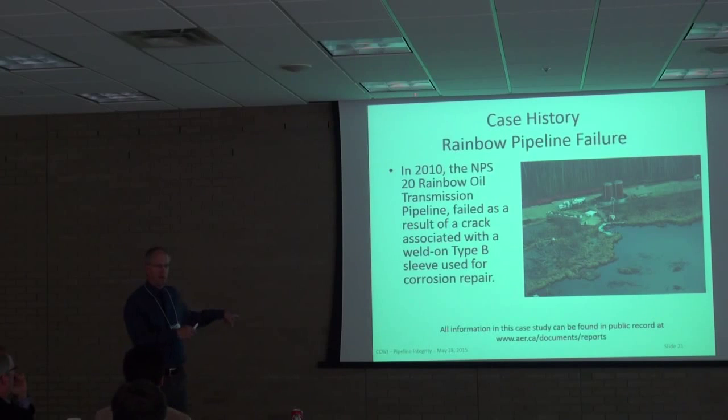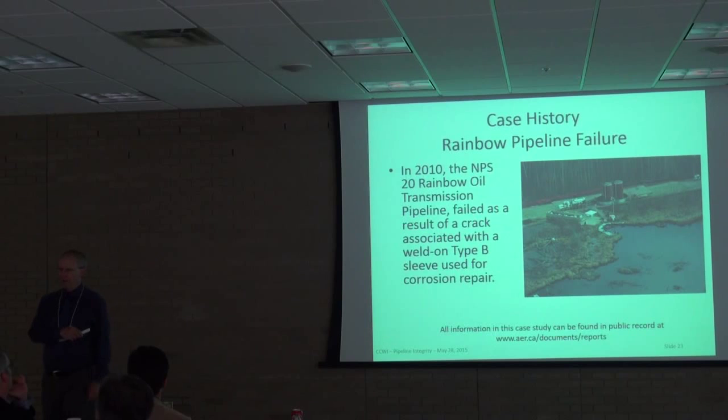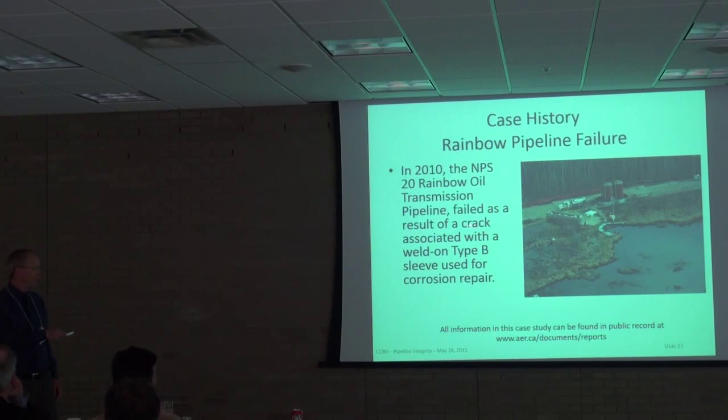Actually, I got involved in a really big failure investigation because of this. One of the other companies that tied into this ended up being shut down for 4 months. And they didn't purge out their line. They couldn't actually do it, and they thought it was okay. The result of the line being shut in with oil and a little bit of water in it was bacteria, and they ended up with a corrosion failure. It cost them millions of dollars, and they abandoned the whole pipeline. It was directly related, because this line failed, they got shut in.